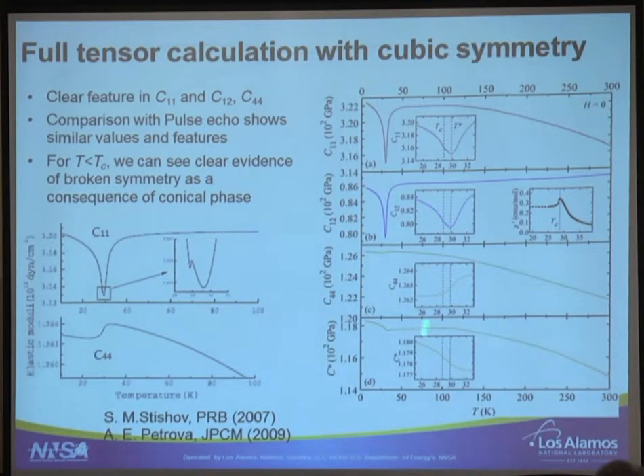Well, the way you do it is, this is the compression along the 1, 0, 0 direction. This is the shear, the pure shear in the 1, 0, 0. And C star is actually the physical quantity, the shear along the 1, 1, 1 direction. So it's what you would get if you measure sound speed in the 1, 1, 1 direction. And this is why people always calculate C star.